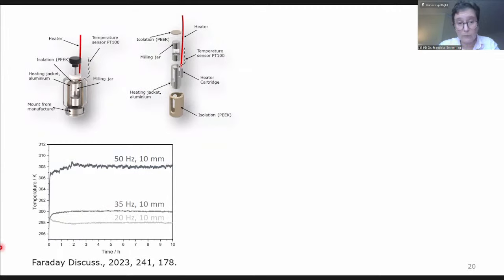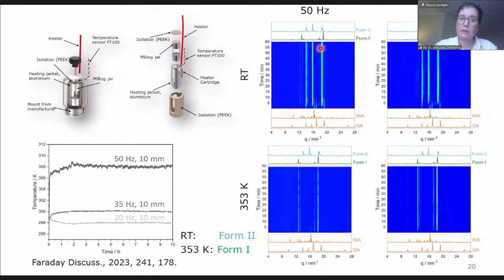So also any temperature changes within the reaction would be counterbalanced by this heating setup. You can also see the changes in temperature we observe depending on the frequency. It's not that much. Sometimes people assume that we have high temperature changes during milling, but in the case of these soft materials, it's a difference of a delta T of maybe 10 K. So it's not really that different. And here you see the data for room temperature. As we already know, we end up with this form two for both frequencies. There is also no intermediate formation of another form. But if we heat now to 353 K, that is 10 K below the transition point we saw in the variable temperature measurement, you can see that we have the formation of form one.